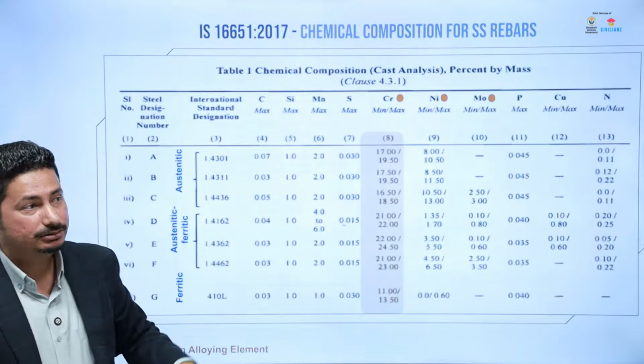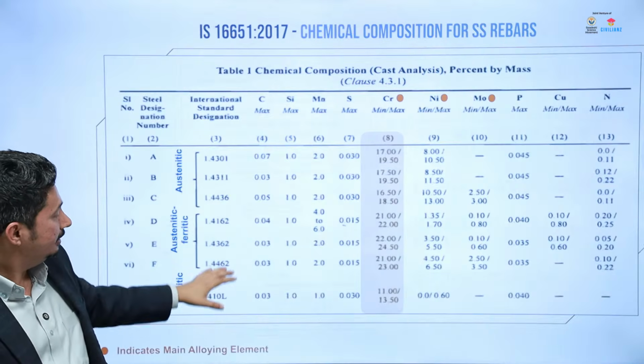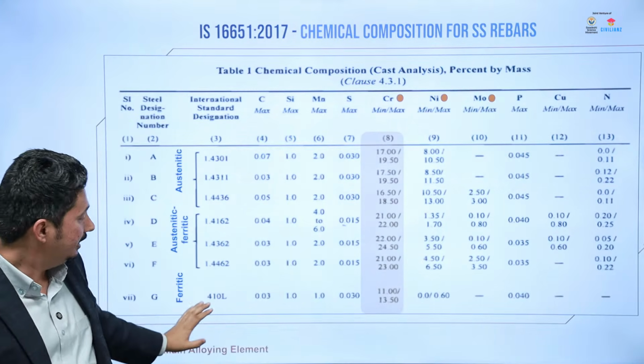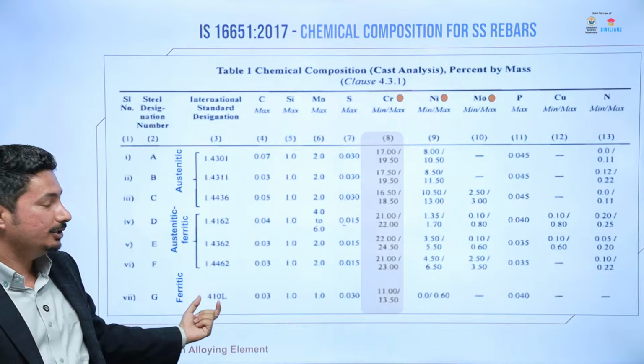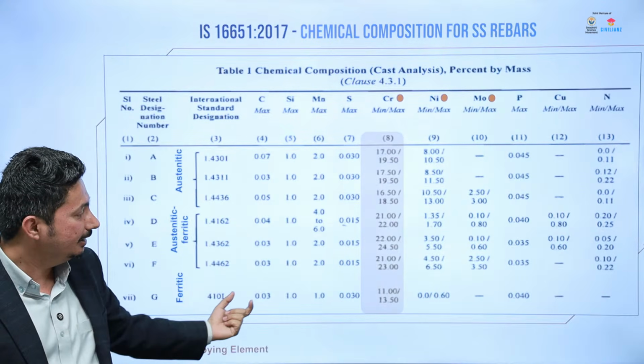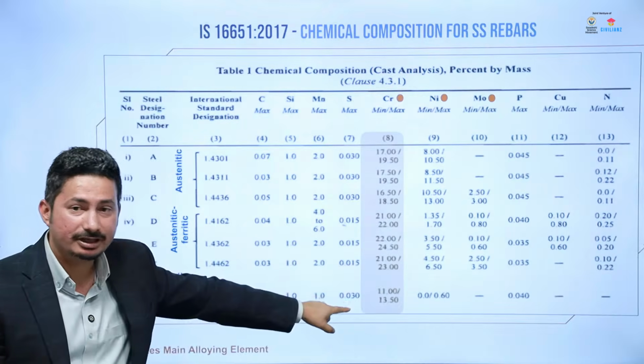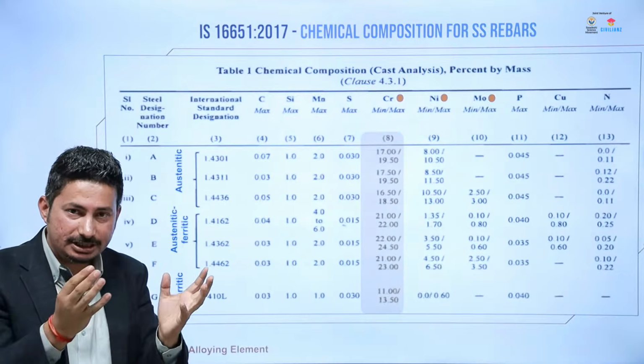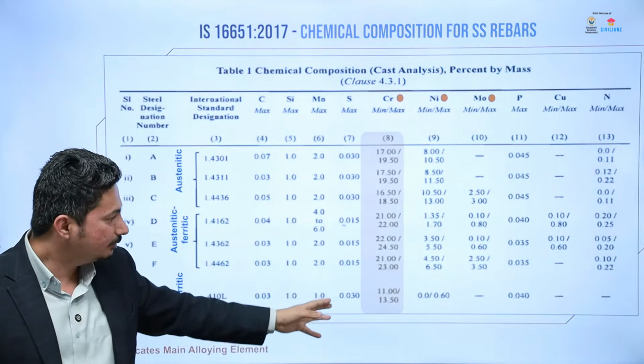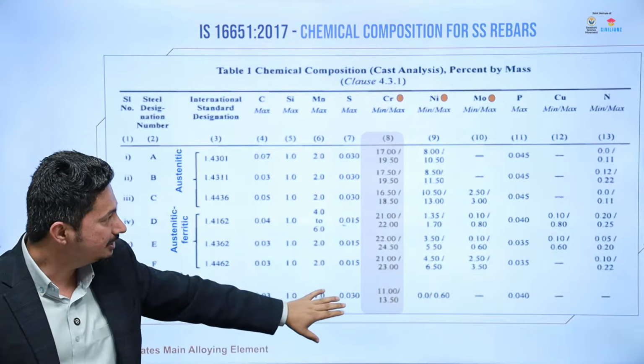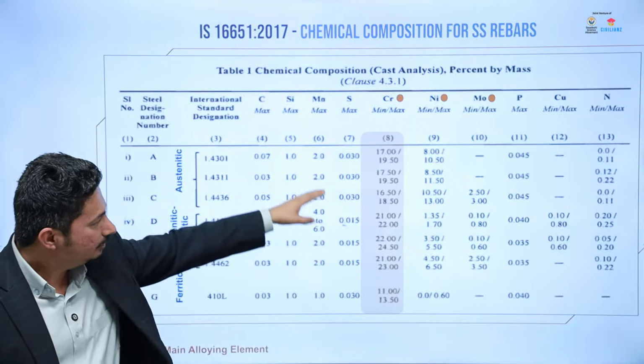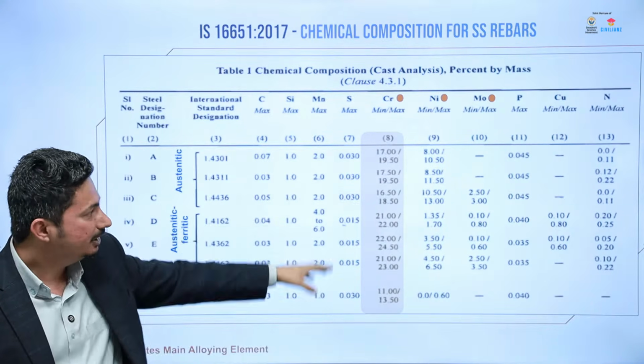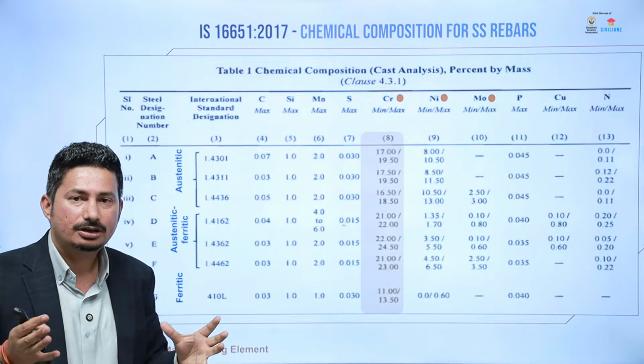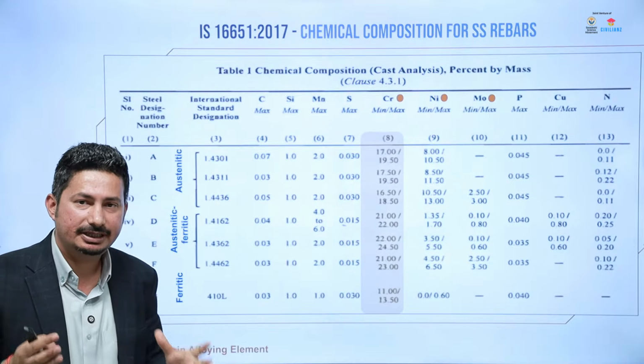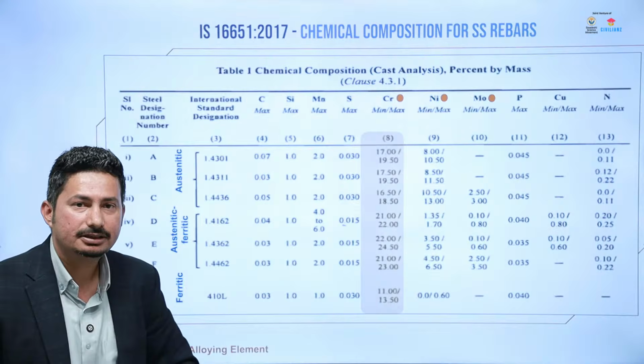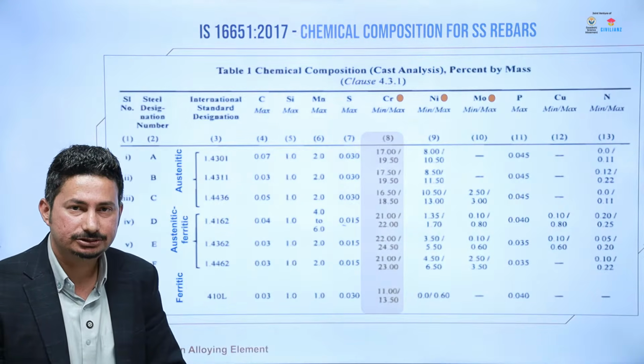Then, as the 7 grades are shown here, in these 7 grades there is even the 410L, which is widely used in India right now. Even in that, chromium is 11 till 13.5%. Remember, chromium creates the chromium oxide layer, so a minimum of 10.5% is required. In this, 11 till 13.5% is available, and it goes till 22, 24% levels. Based on the vicinity and the corrosion resistance that we need, we can choose which material of rebar we should choose.